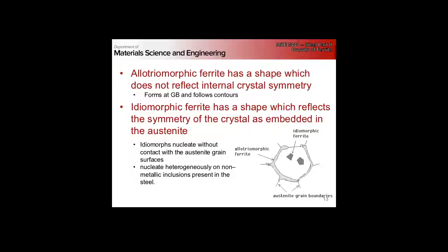We also looked at two different morphologies, which grow in different ways. The first is ferrite allotriomorphs, which grow on the grain boundary and follow the grain contour.